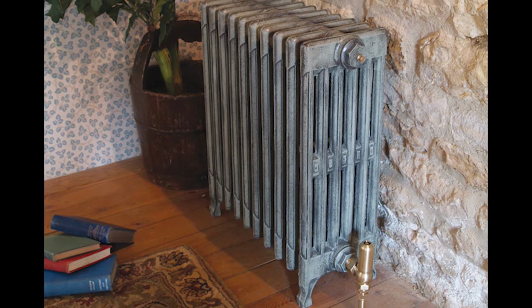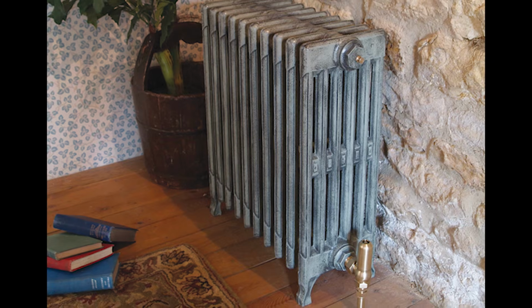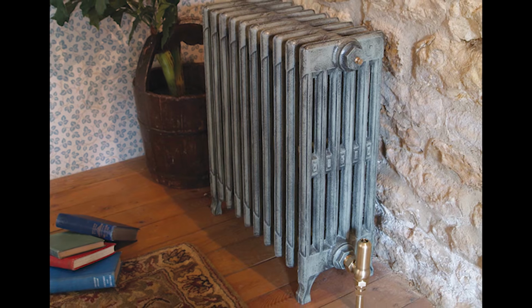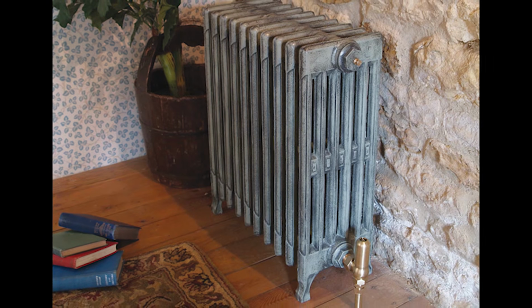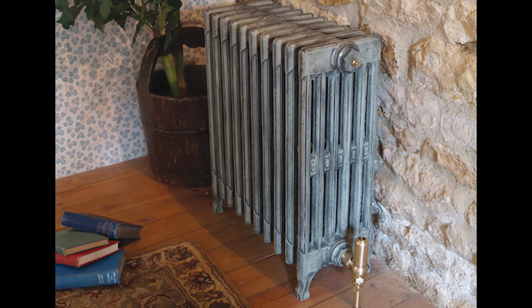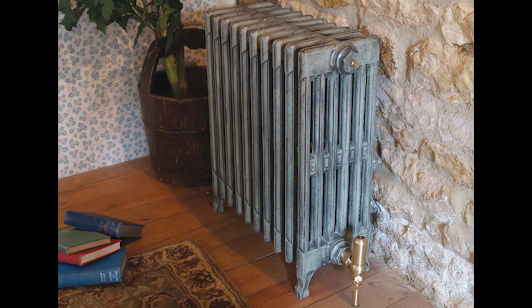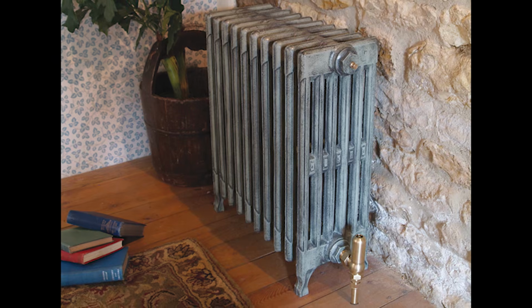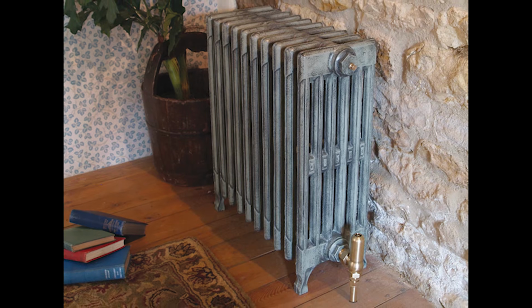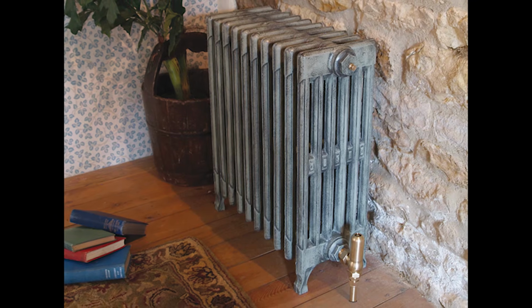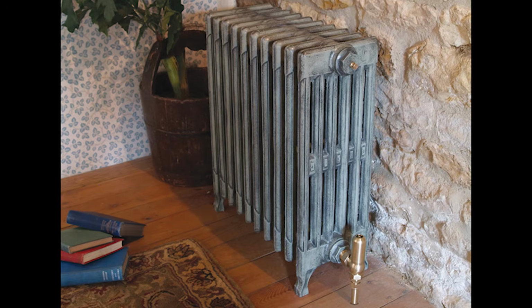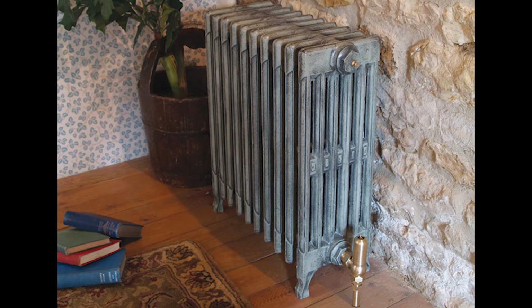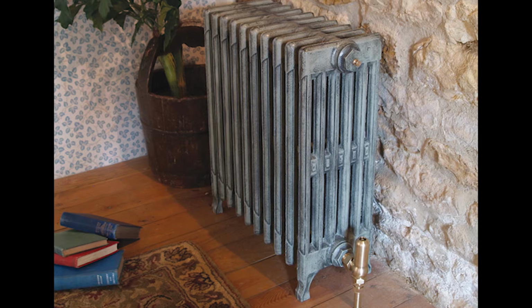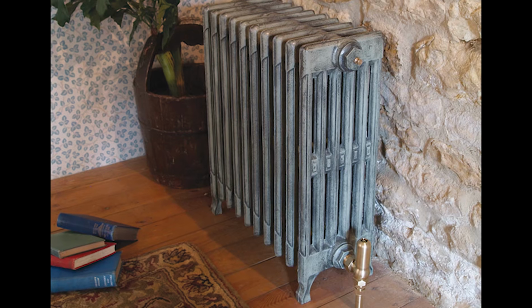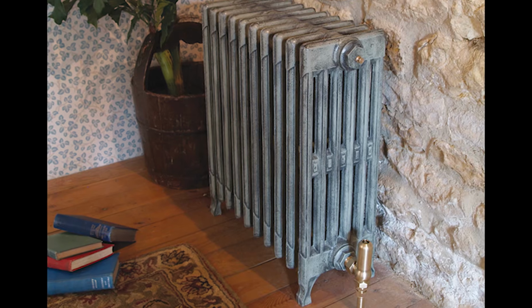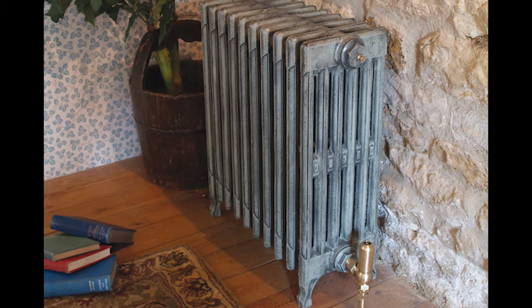Henderson's experiments revealed the mechanism that American foundry workers had observed empirically but never fully understood. When cast iron operated in closed hot water systems with minimal oxygen exposure, the iron surfaces naturally formed a tight adherent layer of magnetite, the black iron oxide with the chemical formula Fe3O4. This magnetite film acted as a barrier that actually slowed further corrosion, creating a self-protecting system that improved with age rather than degrading.